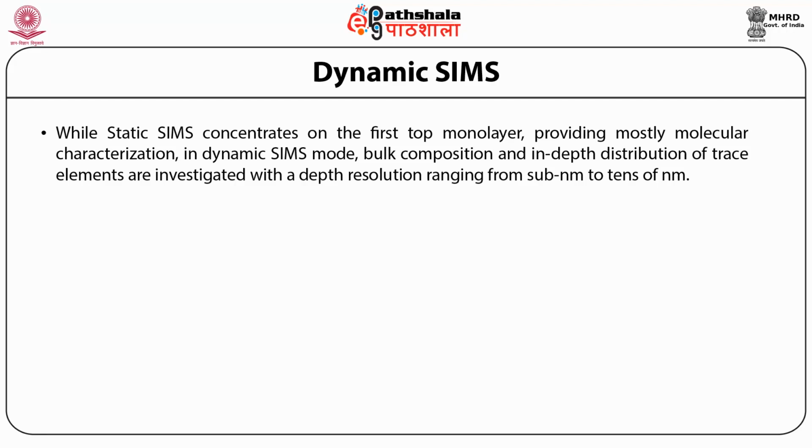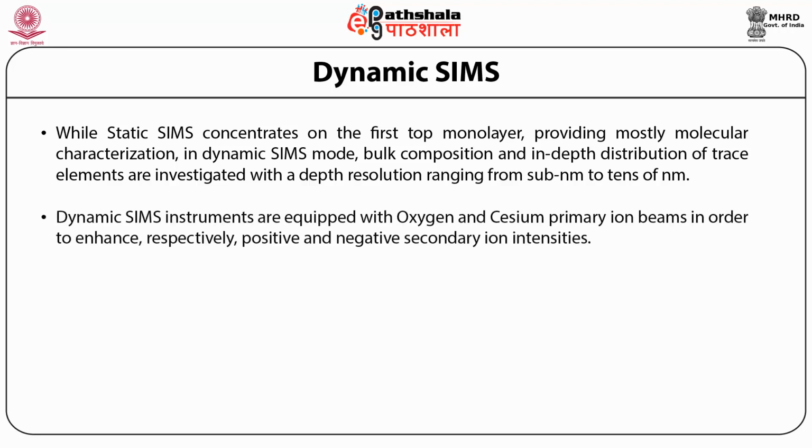In dynamic SIMS mode, bulk composition and in-depth distribution of trace elements are investigated with a depth resolution ranging from sub-nanometer to tens of nanometers. Dynamic SIMS instruments are equipped with oxygen and cesium primary ion beams in order to enhance positive and negative secondary ion intensities respectively.